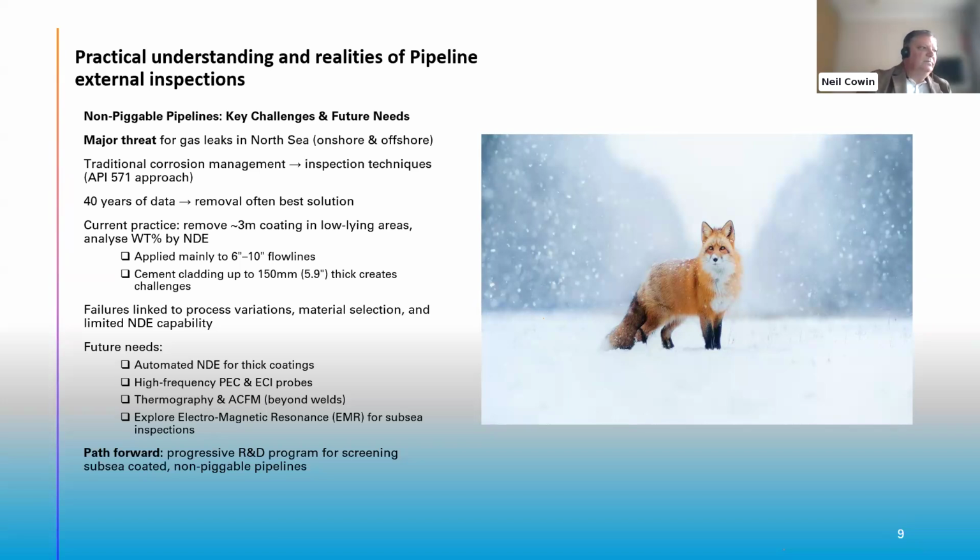So I've had 3 instances where defects have been 1 to 2 millimeters in diametric size, no bigger than 3, and a cluster maybe of them because of MIC. It was external, aerobic MIC, and the depth of it was 6 to 7 to nearly 8 millimeters, and it was a cluster. And I've had MFL tools on 2 occasions miss these kind of defects.